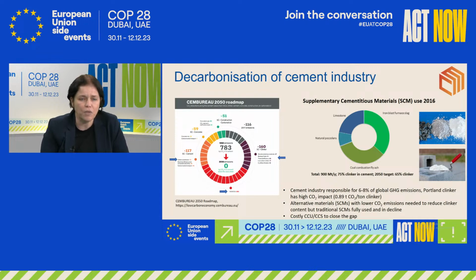So the cement industry already has a long history of looking for alternative materials, which we call supplementary cementitious materials, to replace the Portland clinker and thereby reduce the emissions. And so this is very important to do. They also look at capturing CO2 and storing it to fill up the remaining gap, let's say. As you can see in the figure, a large part of the SCMs that are currently used are coal combustion fly ashes and blast furnace slag from the steel industry.